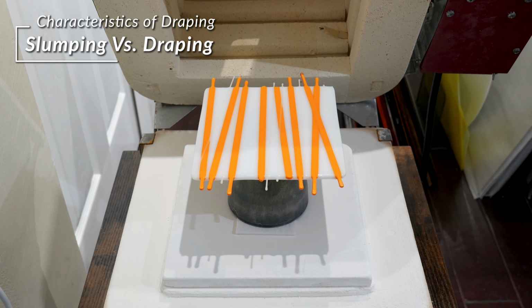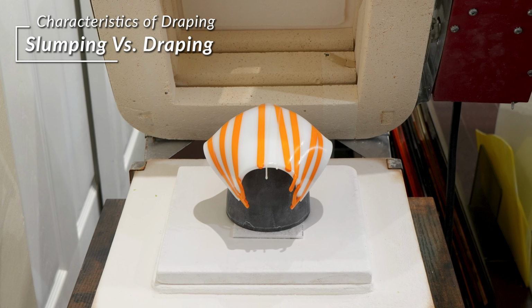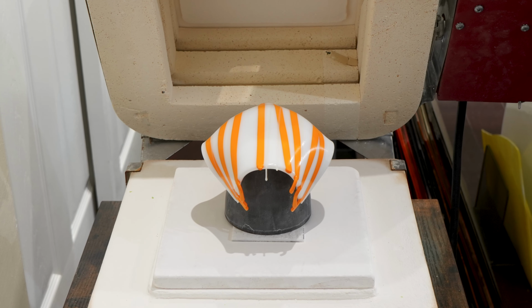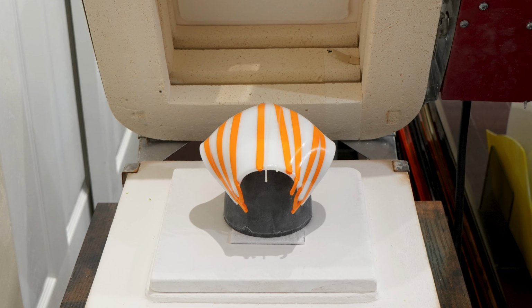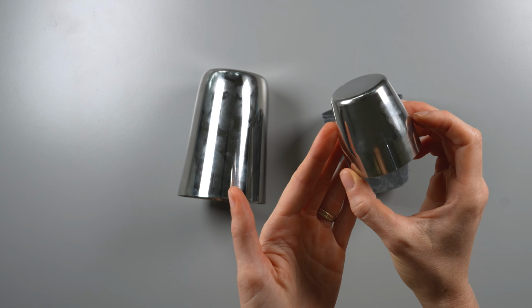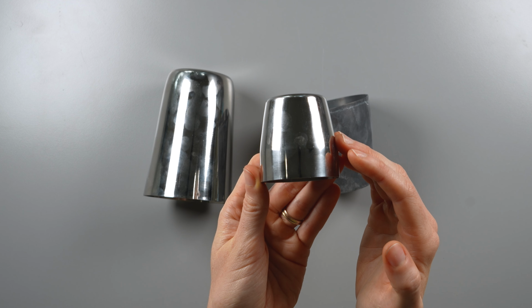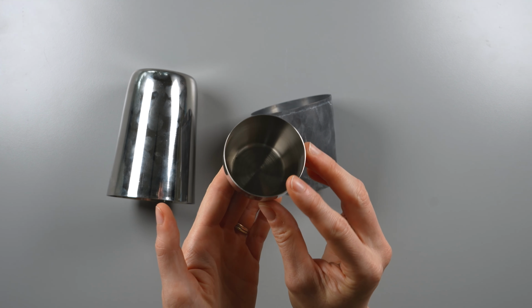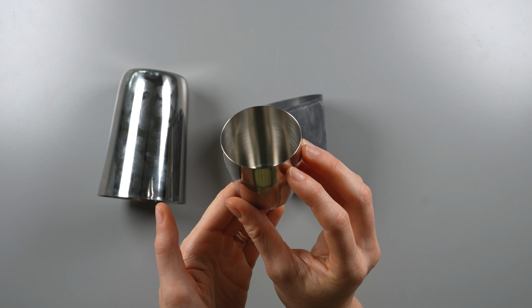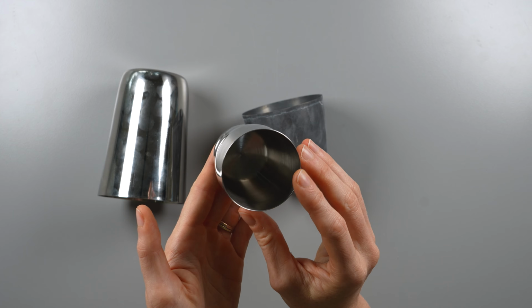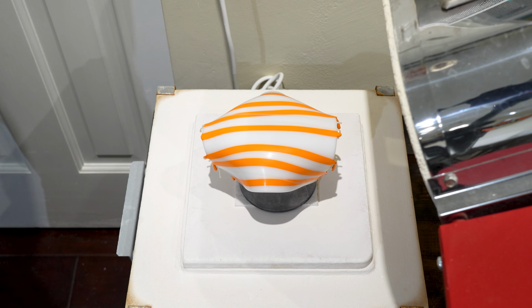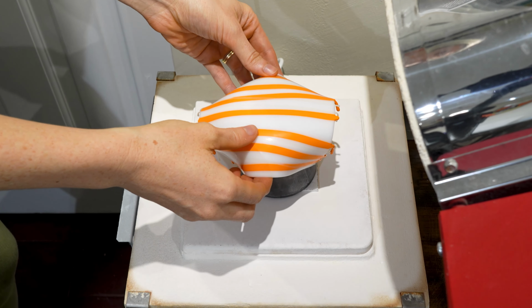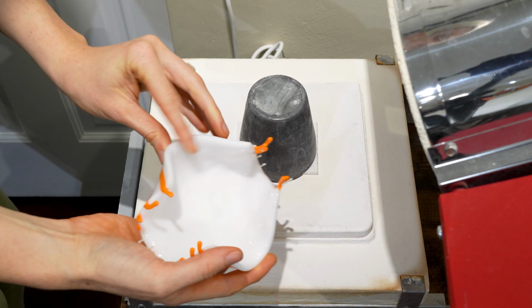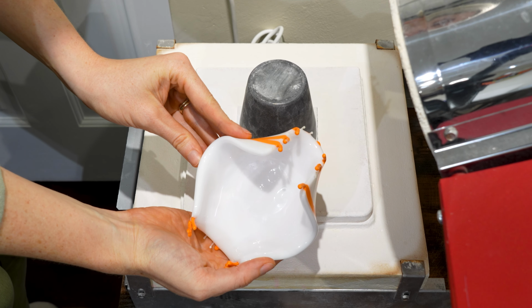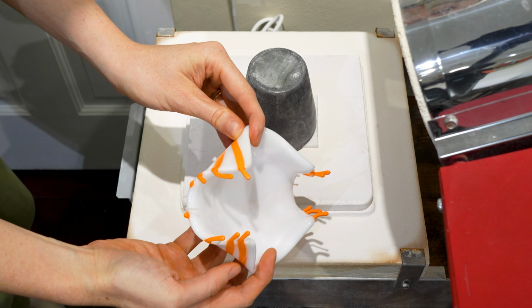Draping, on the other hand, is the process of heating glass over a convex form so that it falls onto and over the form. Draping is typically performed with stainless steel molds because, opposite to ceramic, steel expands and contracts more than glass when heated. This means that as glass cools, it can easily be lifted off of a convex steel mold underneath it because the steel has contracted enough to remain smaller than the glass.